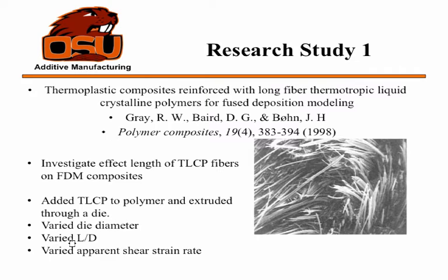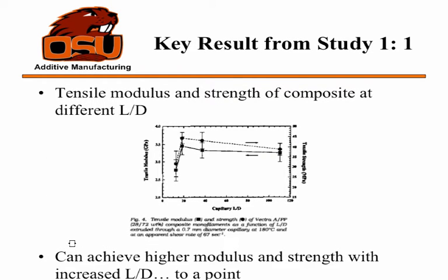But what this guy did was he took a polymer, he put some liquid crystals in there, and he extruded it through a die to try to simulate how a fused deposition filament would be with long fibers in it. So he basically varied, I'm not sure if he varied the amount of the TLCP in it, but he varied the die diameter, the length to diameter ratio, and the apparent shear rates. When he ran some tensile tests on it, he found that a larger length to diameter ratio will increase the modulus and the strength, but only up to a point. So really making this a continuous fiber doesn't look like it's going to do a whole lot. We're not going to have a whole lot of improvement in mechanical properties compared to just maybe a small increase in the length.